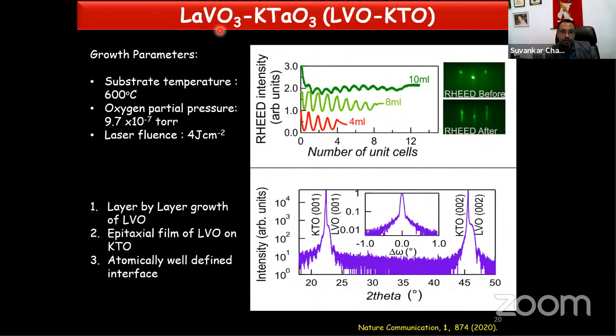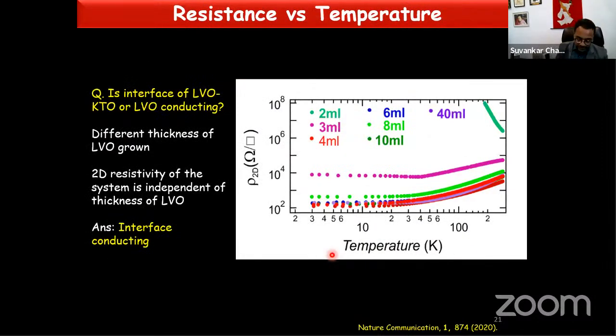So we have grown different numbers of monolayers of lanthanum vanadate on the potassium tantalate substrate, 001 oriented, and this is the RHEED intensity oscillation, which suggests we are growing in a monolayer-by-monolayer fashion, at different numbers of thickness. Then this is the X-ray diffraction pattern, which suggests a beautiful quality thin film has been produced, and you can see the Laue fringes, which suggest that you have a very atomically well-defined interface of lanthanum vanadate and potassium tantalate.